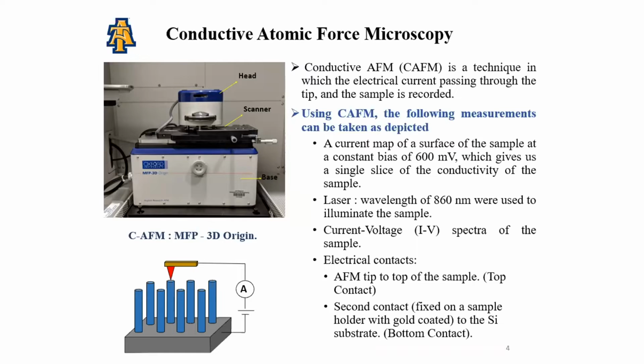Here the electrical characteristics have been investigated using CAFM, a technique in which the electrical current passing through the tip and the sample is recorded. A current map of the surface of the sample at a given bias gives us a single slice of the conductivity of the sample. Current voltage spectra of the sample are measured using CAFM. Titanium iridium conductive tips with a tip radius of 25 nanometers have been used.